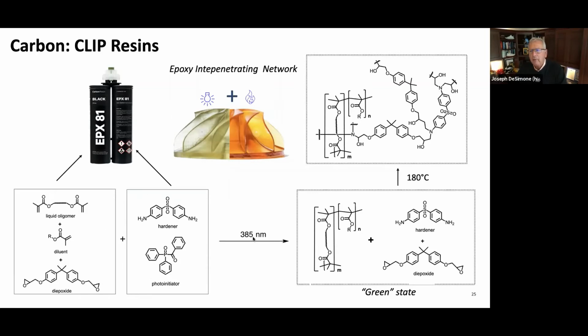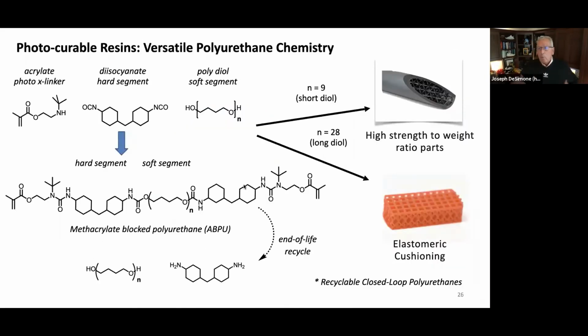You can print it with light at 385, and that defines the shape of the part. And then you have this latent chemistry there that you can fully drive to completion. And we're basically making co-networks with a wide range of different step growth materials with the UV curable defining a shape. So this is orthogonal chemistry that's running in parallel to make co-networks, if you will. And depending on the nature of the step growth, you can make a wide range of materials.